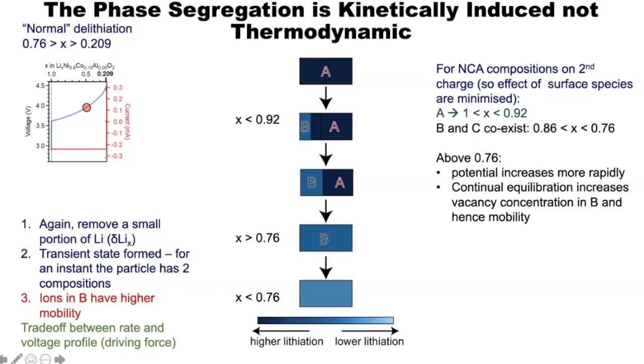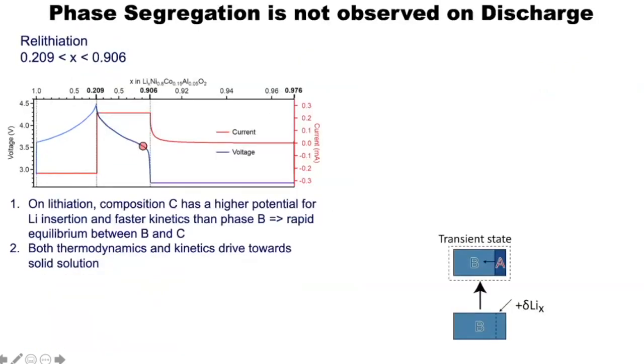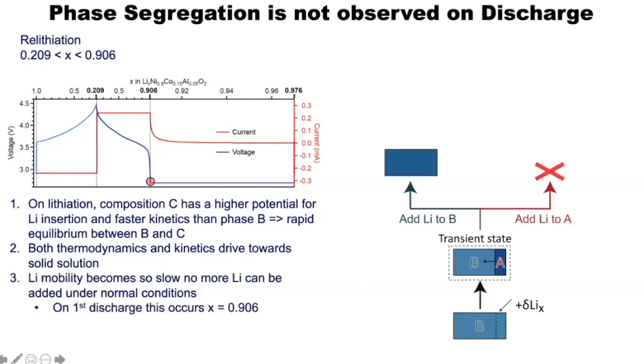When you get to a regime at 0.76 where the lithium mobility is really fast, there are no more kinetic limitations and you go back to single-phase behavior. So just to be very clear, this is not two-phase behavior based on a thermodynamic reason, it's for a kinetic reason. And it has interesting implications because on the way back, you don't see this phase segregation. And I'm going to try and explain this as clearly as I can with these little cartoons.